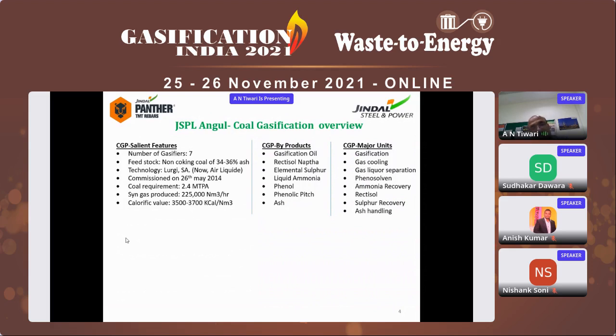Syngas capacity is 225,000 normal cubic meter per hour. The gas which we generate, our calorific values are between 3,500 to 3,700 kilocalorie per normal cubic meter. Because it's a fixed bed, we generate around 7 byproducts. We call them the gasification oil, which we are consuming internally. Rectisol naphtha, elemental sulfur, liquid ammonia, phenol, phenolic pitch, and tar, which we are selling in the market.